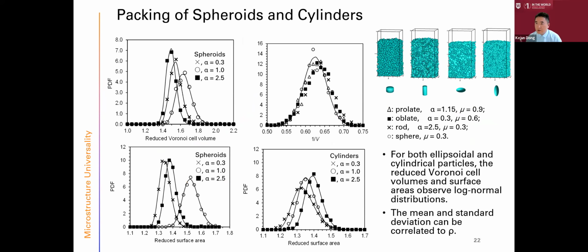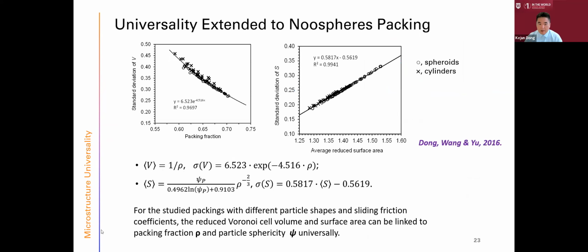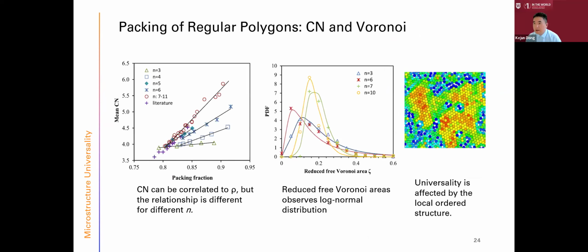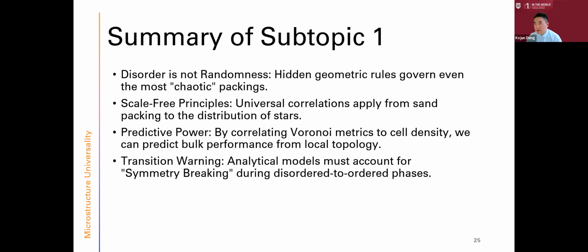And that one can also be extended to the packing of non-spherical particles like the cylinders and the ellipsoid particles. So their Voronoi cell volume and surface area can be linked to packing fraction also, and their sphericity. So that's a successful extension of the microstructure universality we found in the monosize sphere packings. And when we check the 2D polygons, we can find the distribution has a similar form, but maybe it cannot be simply linked with the packing fraction. And that, from our observation, actually comes from some local order structure, which is more easily seen in the 2D packings. Then that comes to our second topic.